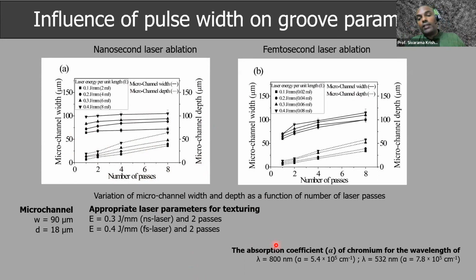One should note here that femtosecond pulses were used at a central wavelength in the near infrared of 800 nanometers, whereas for the nanosecond pulses, this was at 532. The absorption coefficient of chromium is a bit different. It's about 50% different, but the mechanism of interaction is significantly different. In the case of femtosecond pulses, it's multi-photon absorption and ionization, whereas nanosecond pulses is more a heat dominated process.